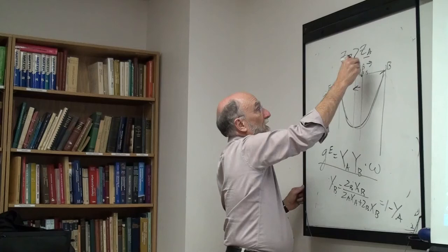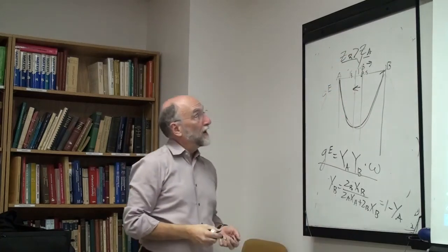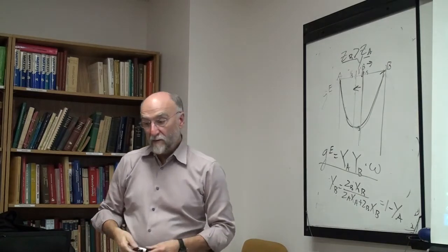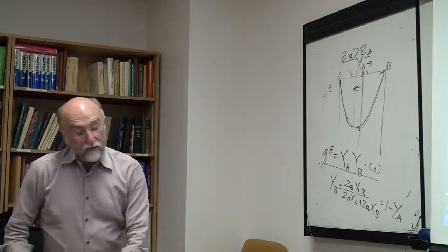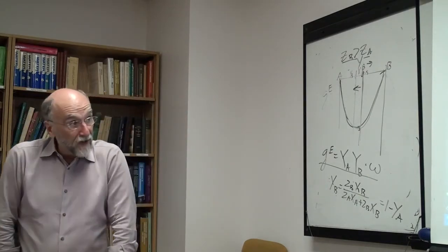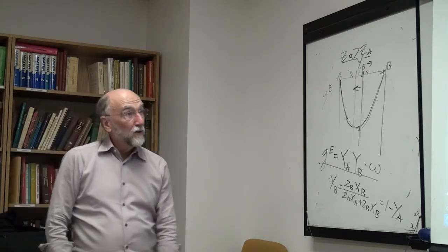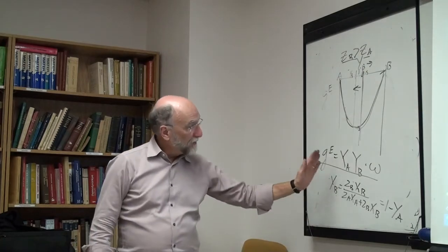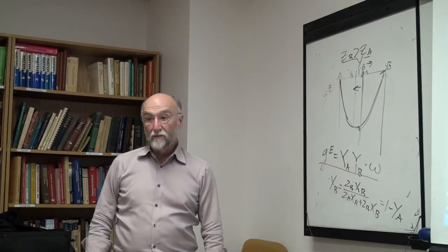Or in other words, if you plot it in coordinates YB, you simply shift your minimum back to 50%. And it has been shown in a number of liquid solutions that we can get a nicer fit with just one term or fewer terms to many systems without having this whole problem by replacing the x's by the equivalent fractions.